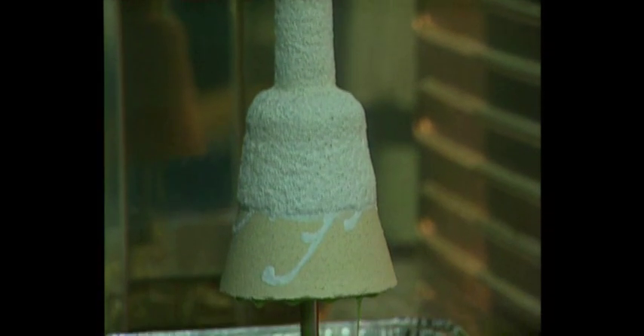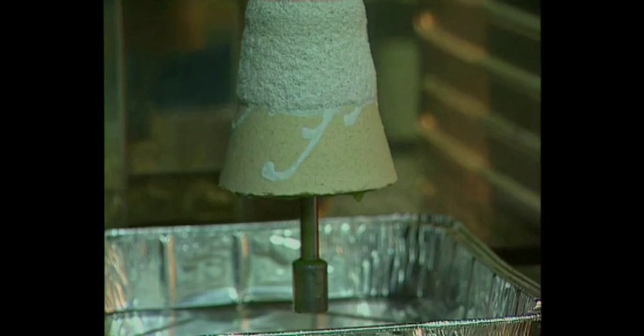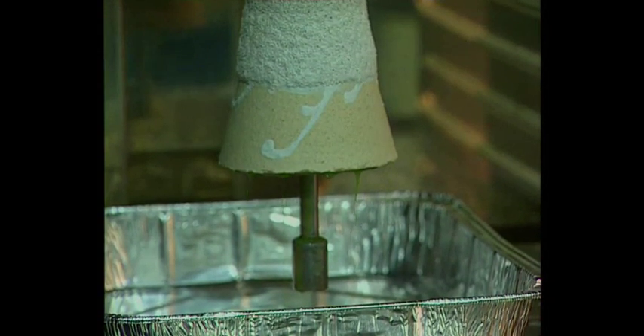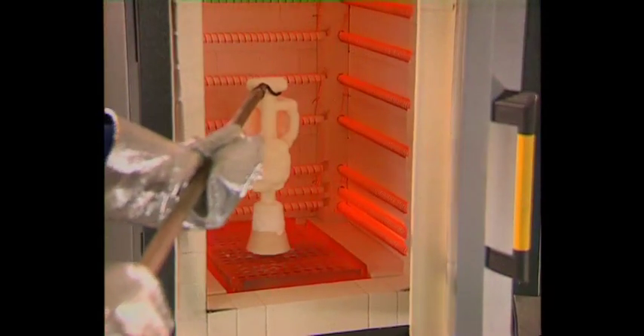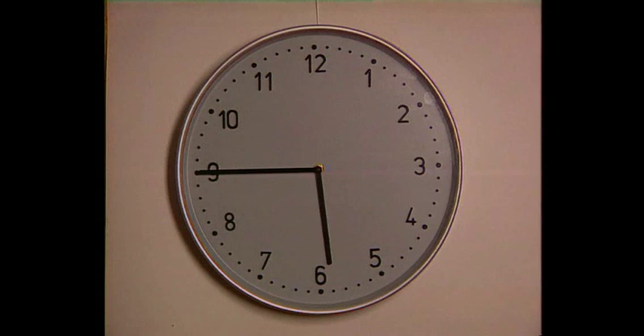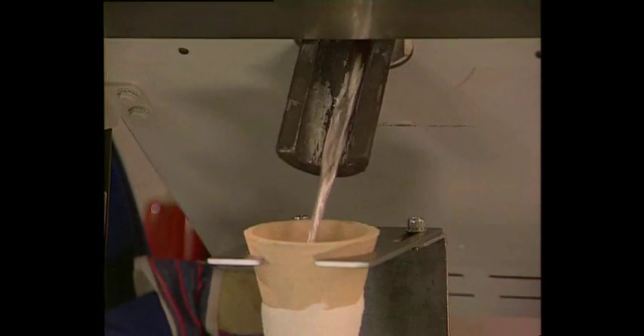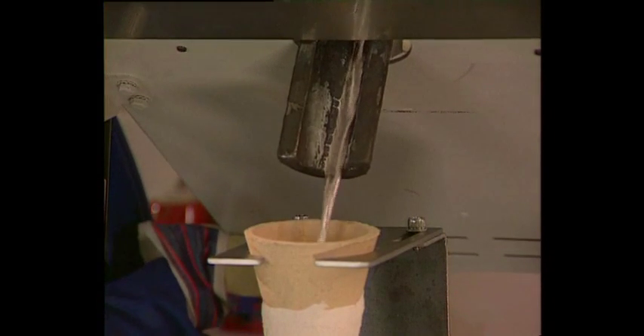The melting process can be started immediately at 150 degrees Celsius for 45 minutes. After a burning time of one hour at 850 degrees Celsius, and after a short cooling time, the casting can be started. Six hours after the process has started, the part is ready and can be finished.